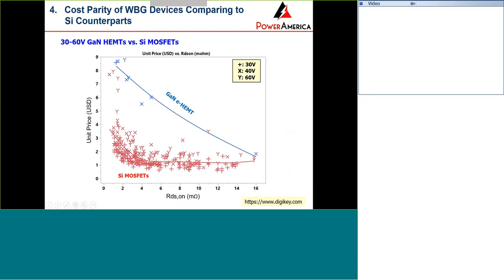This figure compares gallium nitride devices at a lower voltage, 30 to 60 volts, versus silicon MOSFET shown in red. You will see that enhancement-mode gallium nitride is generally more expensive than silicon MOSFET counterparts. But for some on-resistance values, for example less than 2 milliohm, and also some with high resistance, at least based on the DigiKey numbers, the price is similar to the silicon MOSFET per unit.